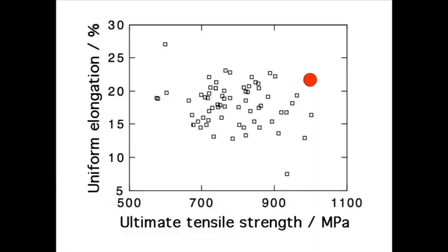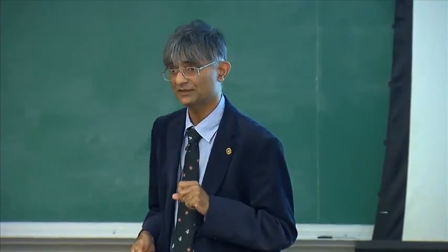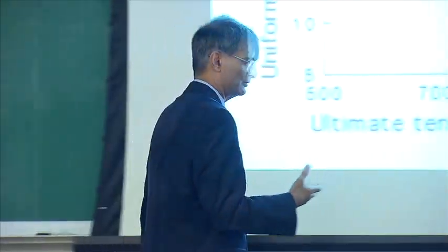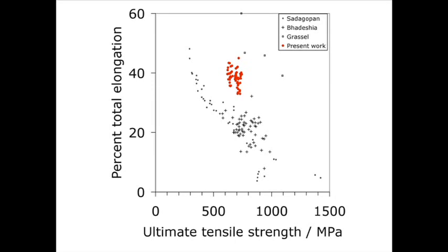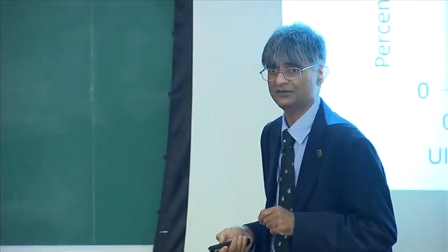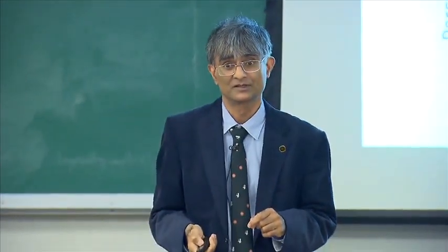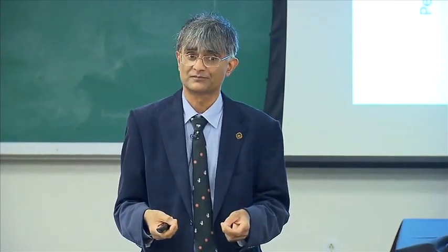And if you look at all the commercial TRIP-assisted steels, this is the alloy obtained the first go, okay, from the prediction to making a small melt. And then, of course, there's a lot of other work to be done to measure weldability and hundreds of other parameters. But that gap that I was telling you about is filled. Okay? And furthermore, the addition of aluminium reduces the density of the steel by 5%. Okay? So the specific strength is even higher. Yeah?